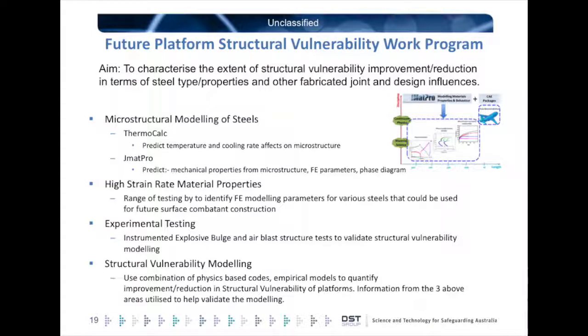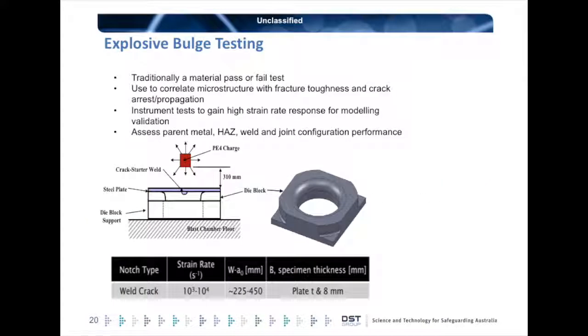High strain rate properties of materials. We've done a lot of work with Nordmetall in Germany in terms of giving those steel samples. They do high strain rate testing of those steels, well, relatively high strain rate testing. And I was going to say we do some high strain rate testing. But also there's been a combination of experimental testing, such as using explosive bulge tests, which I've got a few slides on. And those three areas come together in our structural vulnerability model, which I'll show a little bit more. But just to talk about some of the high strain rate material testing.